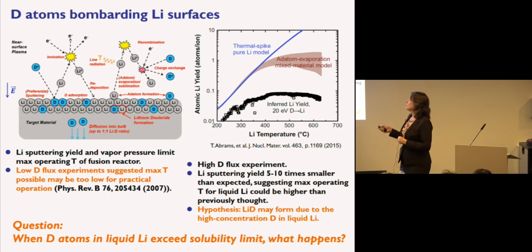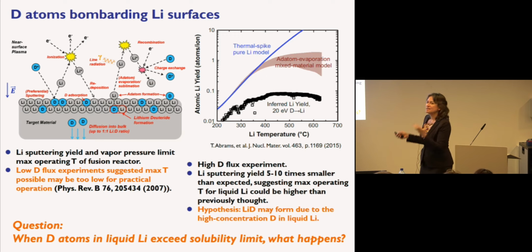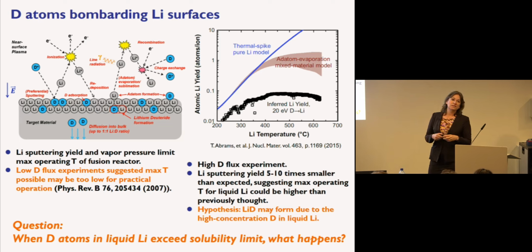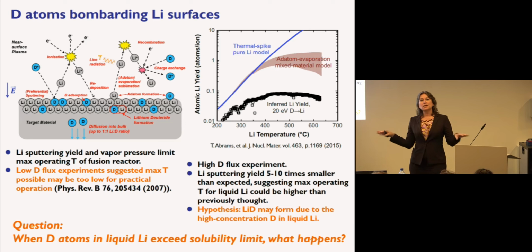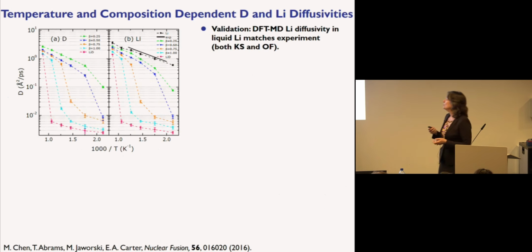Now, here's the problem. Deuterium has a very localized electron density, and the liquid lithium, as I just explained to you, has a very delocalized electron density. It's nearly free electron-like. We tried modeling this with orbital-free molecular dynamics, orbital-free DFT, and we could not properly describe both at the same time, and we still don't have accurate enough methods to describe a delocalized electron density at the same time as a localized electron density. So we had to move to using Kohn-Sham density functional theory.